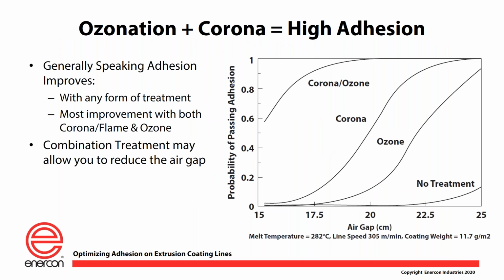And here again, you can see in this slide, if you add yet one other step, so let's say we have our ozone applicator in there, it's doing its job, but maybe we also added a surface treater that's treating that main substrate prior to it getting into the application. It can be really impactful, right? And you can see it on the chart with no treatment versus just ozone treatment. And then when you add corona treatment on top of that, your adhesion profile is tremendously improved, right?